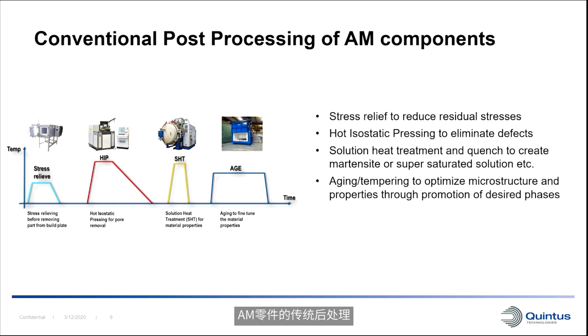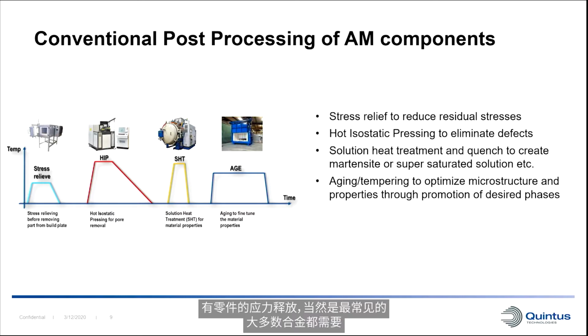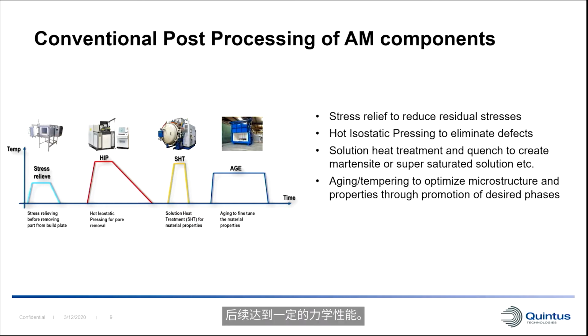Conventional post-processing of AM parts has several steps, and in this case for laser, you can see stress relief of the parts is quite common, of course, and needed for most alloys. And then you have a HIP, usually, for high-end parts, and solution heat treatment, and then aging for some of the precipitation alloys, where we want to achieve a certain mechanical property later on.